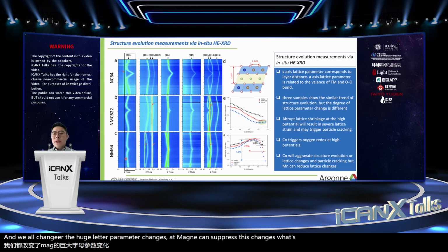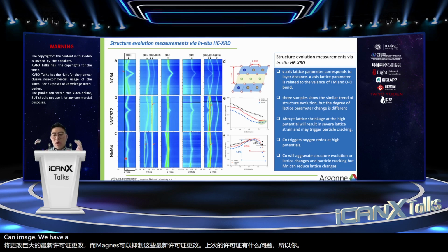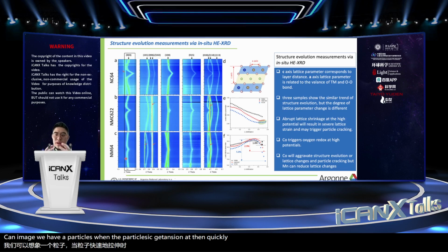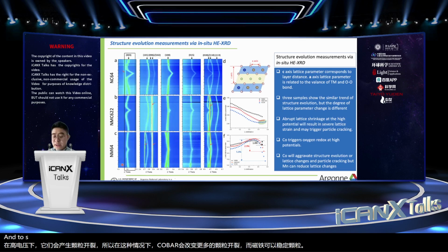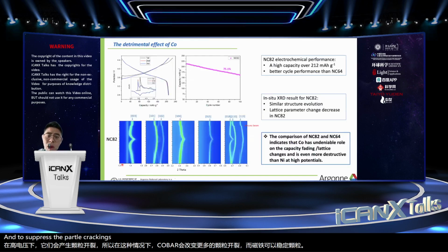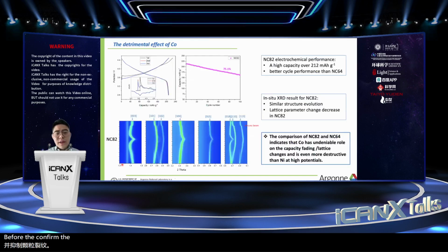What's wrong with the lattice parameter changes? So you can imagine we have a particle. When the particle expands and then quickly contracts at high voltage, it will generate particle cracking. So in this case, cobalt will trigger more particle cracking, and the manganese can stabilize the particle and suppress the particle cracking.